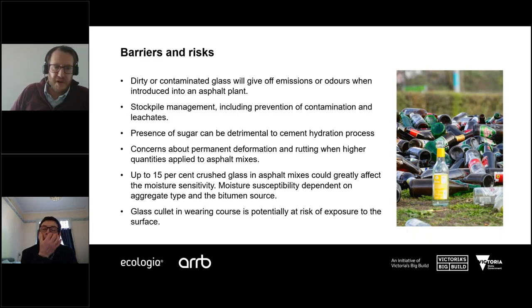We also need to be mindful of stockpile management. So again, we're always hearing about the large amounts of recycled crushed glass that's stockpiled around the state. And if we're going to have stockpiles of crushed product around, we just need to be mindful that we manage those stockpiles to prevent both contamination and leachates getting into underlying ground and soil. So potentially lining our stockpiles to prevent them from leaching directly into the soil.